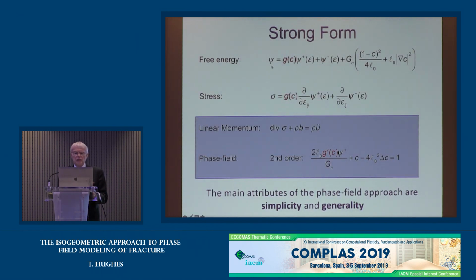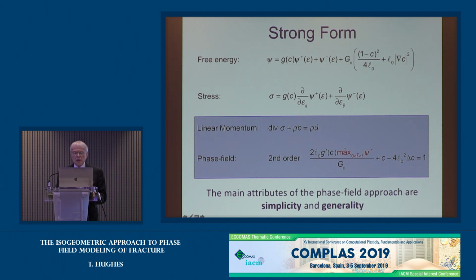Well, the strong form of the equations emanates from this free energy, which contains the integrands of the volume integrals: the elastic energy, the damage, and also the surface energy. This is the expression for the damage stress. So you're given the usual linear momentum equations to solve and a second order in space phase field equation. And this is just the variational equation obtained by differentiating this expression with respect to C. So again, you can see it's second order. And you can see if there is no damage, in other words, if this is zero, then C would just equal one. The material would be unaffected. Now, you can introduce, in sort of a non-variational format, an entropy switch, and that will prevent the healing of cracks. Once they're cracked, they're done.